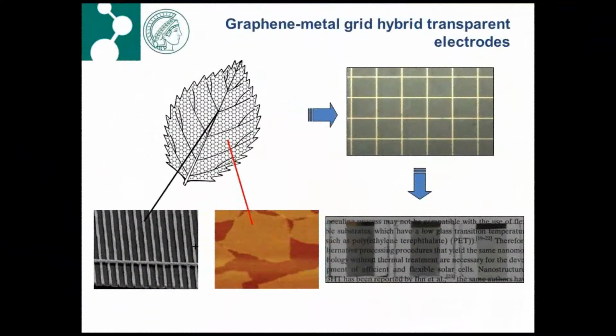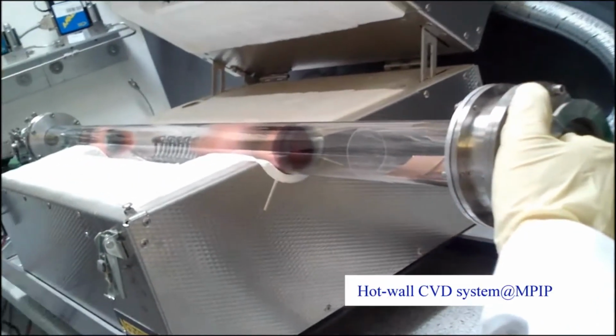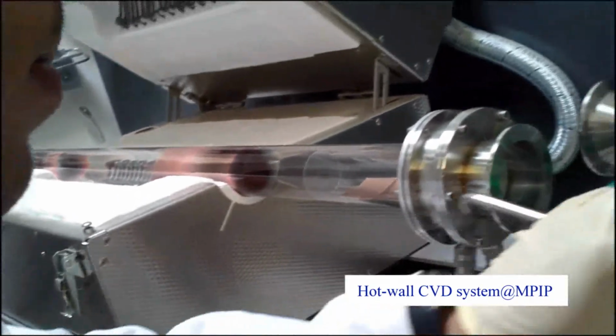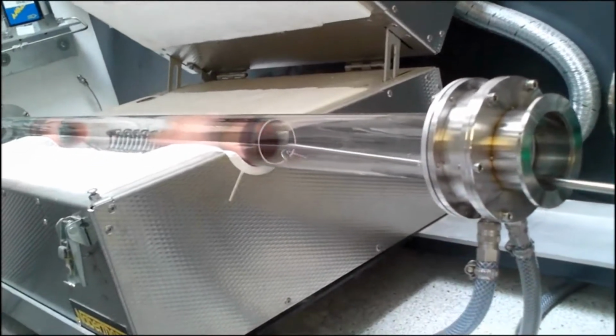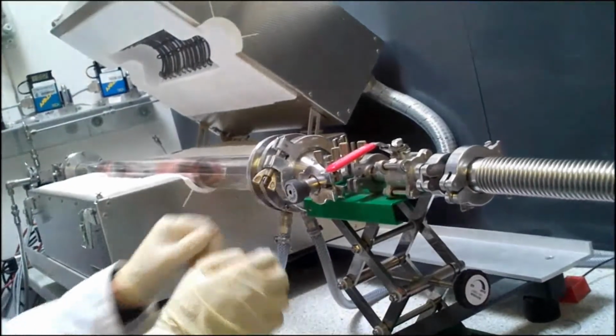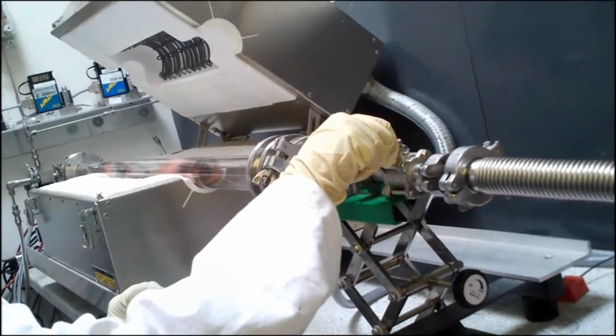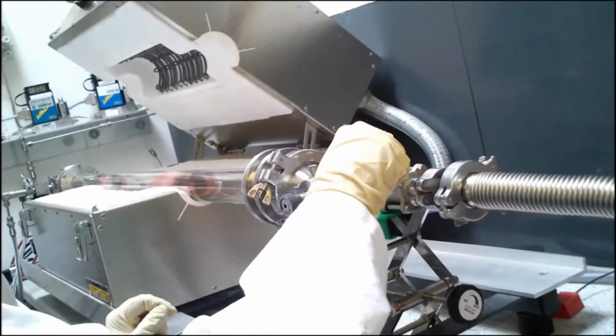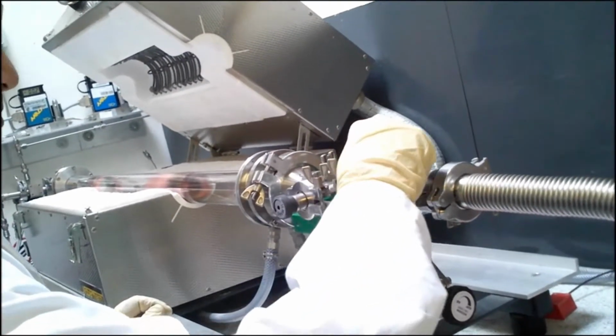Samples with a sheet resistance of about 450 ohm per square with transmittance over 95% were obtained. The sheet resistance was further decreased by the combination of gold grid and graphene, resulting in a sheet resistance of about 30 ohm per square and around 80% transmittance.